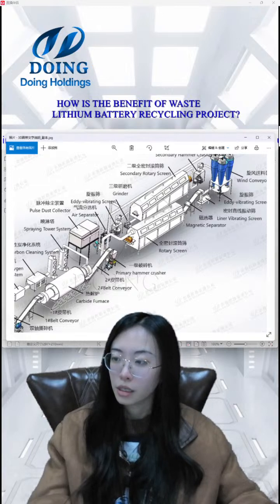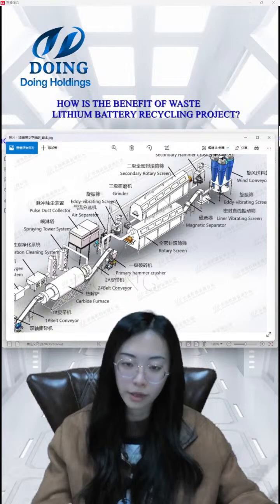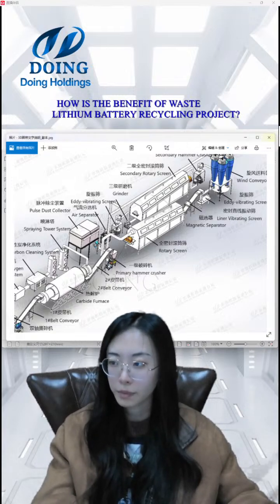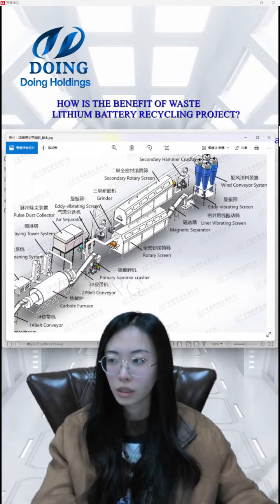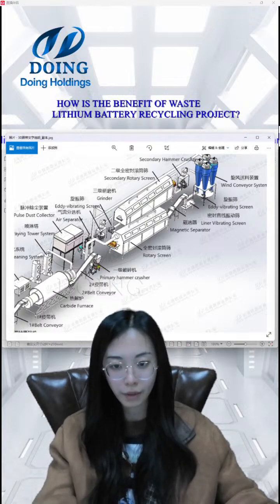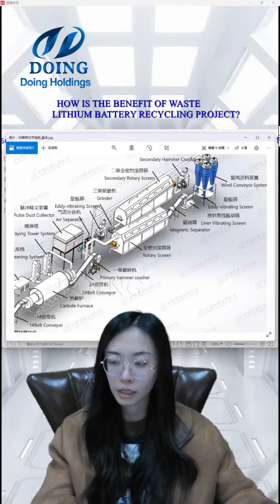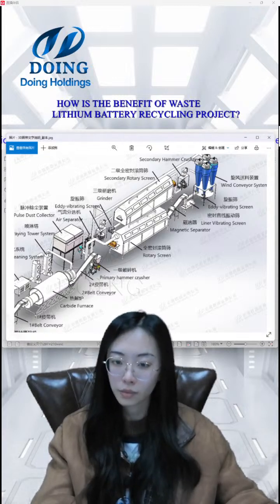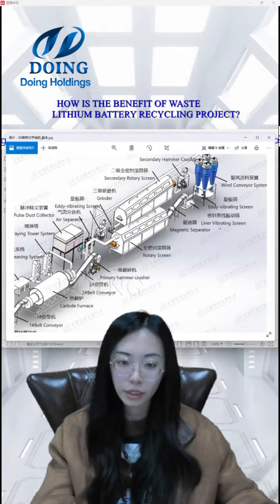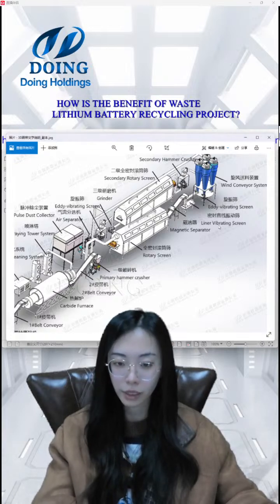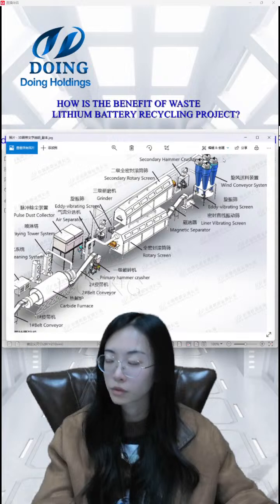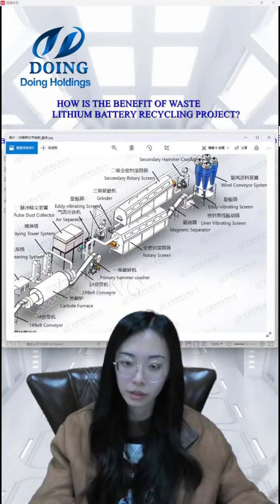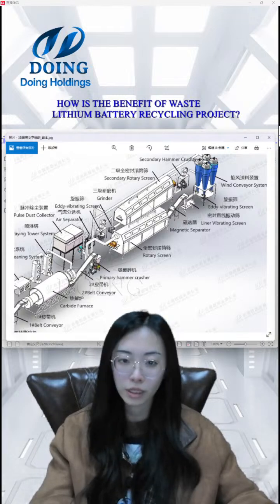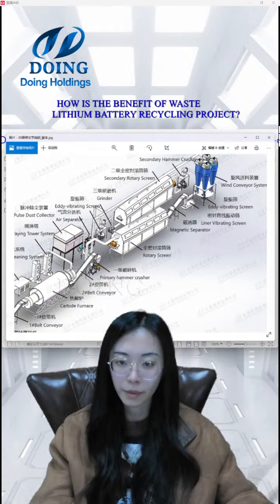Then it will come to the second crusher, the primary hammer crusher using the hammer blade step, and then the rotary screen to control it, to recycle the black powder for 60%, and then a magnetic separator to separate the iron, and then a linear vibrating screen to separate and recover the diaphragm. The eddy vibrating screen also separates the black powder, with a conveyor for the sealed conveying transportation step, and then puts it into the secondary screen. In this step we can recycle more than 95% of the black powder.